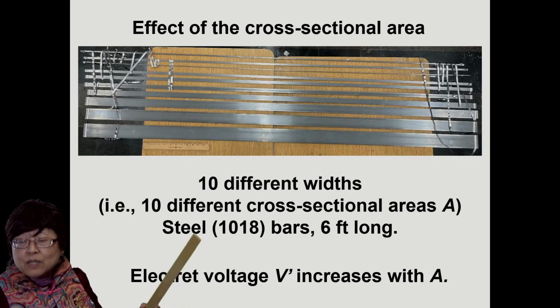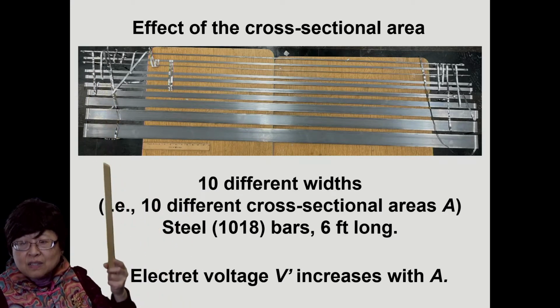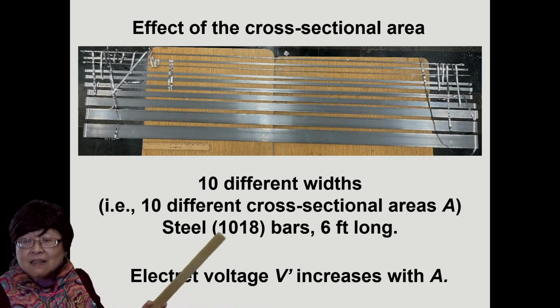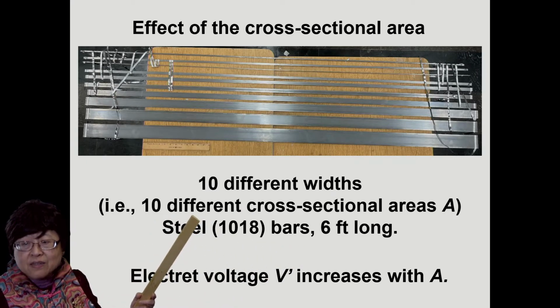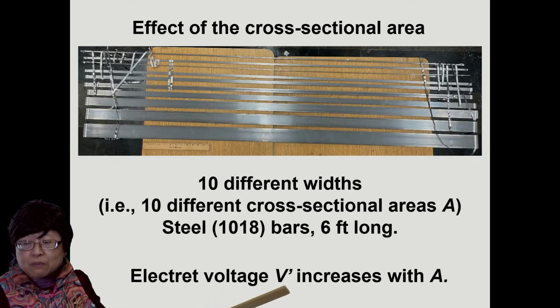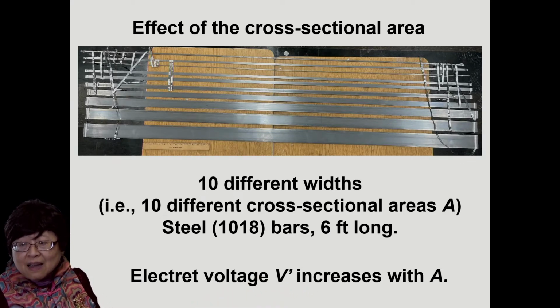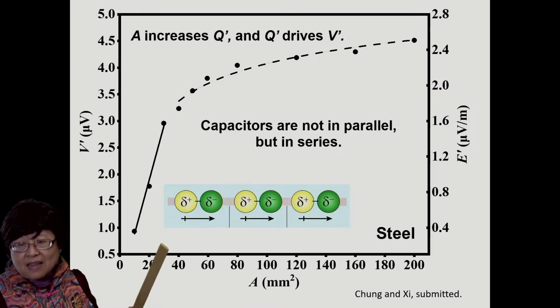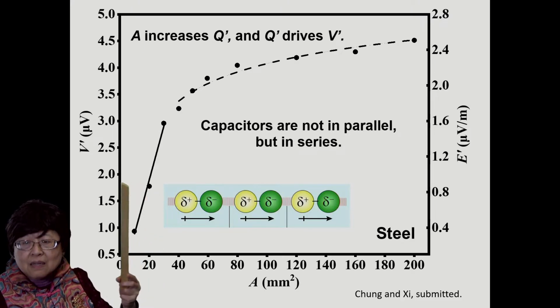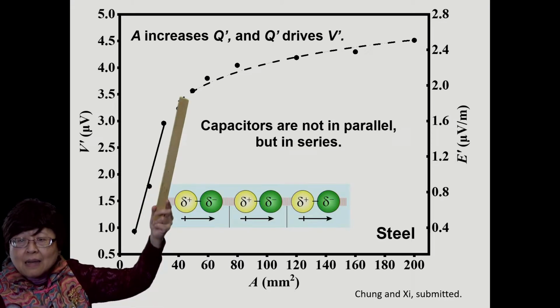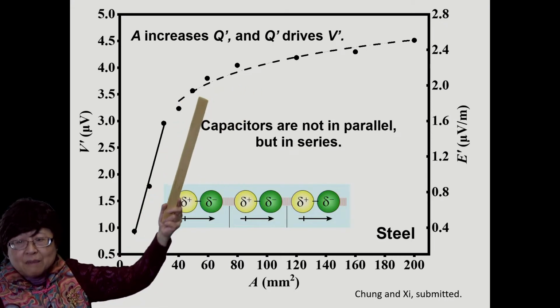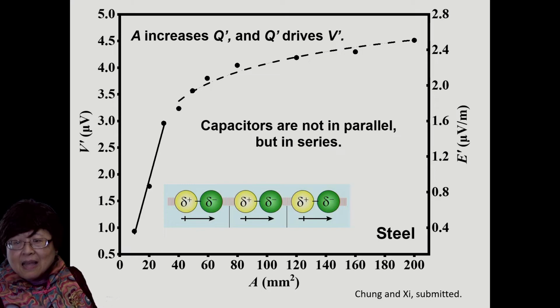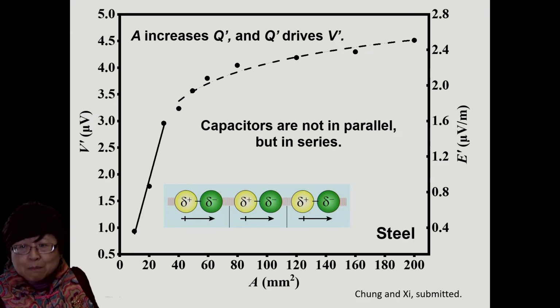Okay. So we took 10 different widths of steel bars, each 6 feet long. So we have 10 different cross-sectional areas, A, and we studied the electret voltage V prime versus A and found that the voltage increases with A like so. In the low A arena, the V prime is roughly linear with the A. But in the high A arena, it's not linear, but still the V prime keeps increasing with increasing A. Okay? And this is because the A increases the Q prime, and the Q prime drives the V.